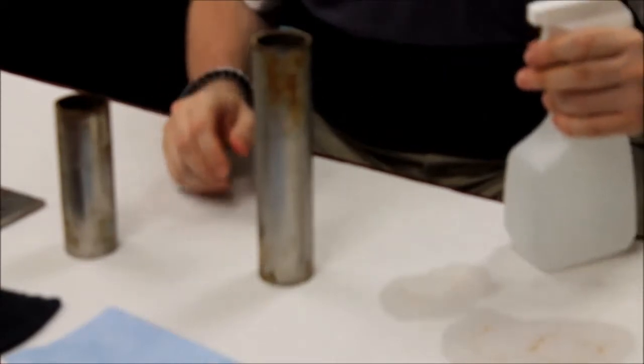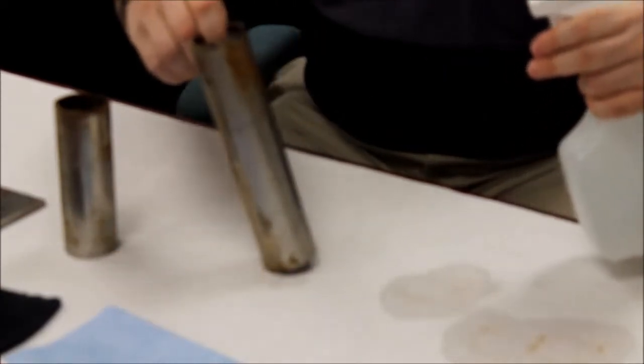After you apply the product, it should sit on the surface for about 20 to 30 minutes at room temperature. If it's colder than that, the reaction slows down, so you need to give it extra time, about doubling the time for every 20 degrees drop below 70 Fahrenheit. If it's warmer than that, especially outside on a sunny day, make sure the CitriSurf stays wet. The reaction stops working if things dry out. Mist slightly with some water if needed to keep things moist.